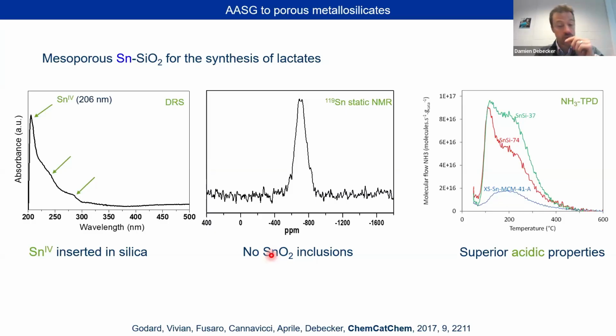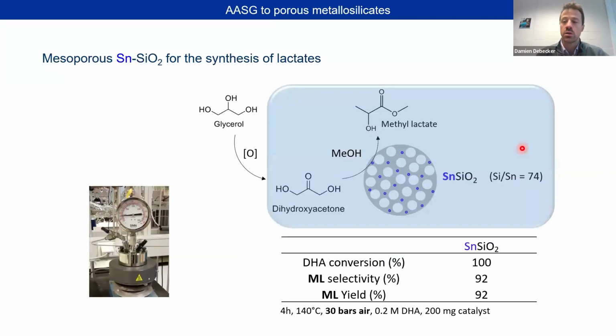The fact that we have a very good dispersion of this tin means that we have a large acidity. This is the acidity that is measured by ammonia chemisorption. And if we compare our aerosol-made catalyst with a catalyst made by standard sol-gel, we see that we have much higher acidity. It's basically Lewis acidity that is needed in this reaction. So I will not show you many catalytic results on that catalyst, just to show you that with this one, we managed to have a full conversion and almost full selectivity.